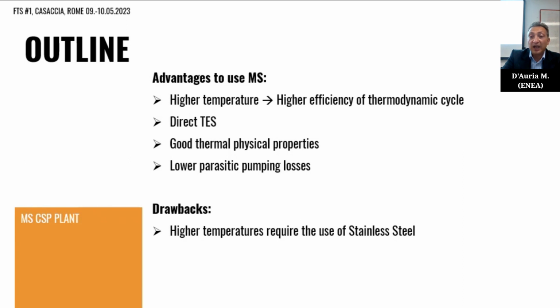Molten salts have high density, high heat capacity, and high thermal stability, even at elevated temperature. These properties are important features for the heat transfer fluid. Compared to thermal oil, parasitic pumping losses are lower with molten salt because the volumetric flow and the pressure drop are lower. This is another benefit, obviously, of using molten salt in the solar field instead of thermal oil.